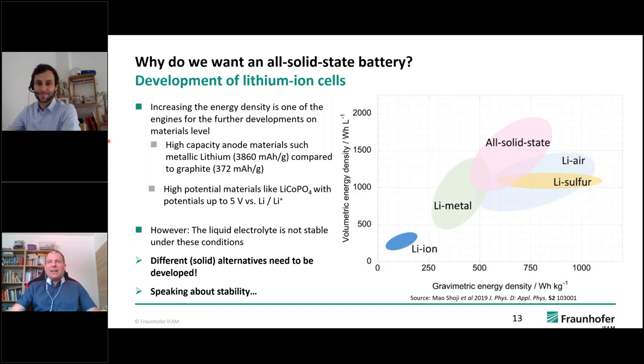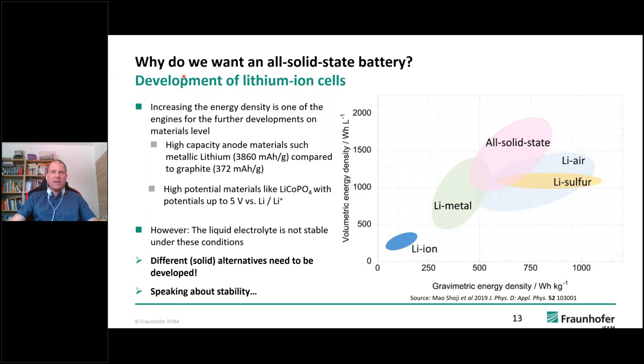Okay. So, as I said, all solid state batteries and lithium metal give us high energy density. But the problem that we have is that the liquid electrolyte is not stable under these conditions. So with these high potentials, we get problems using the system that we have at the moment. And this leads us to a very important point, the stability. So we need some alternative, a solid alternative, just because we're talking about solid state batteries. There are also liquid alternatives, but solid alternatives also need to be developed. But stability is a big issue when talking about lithium ion batteries.